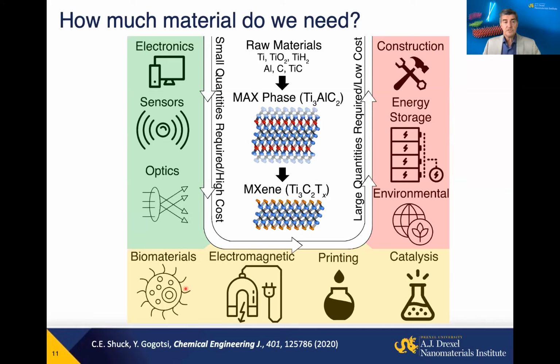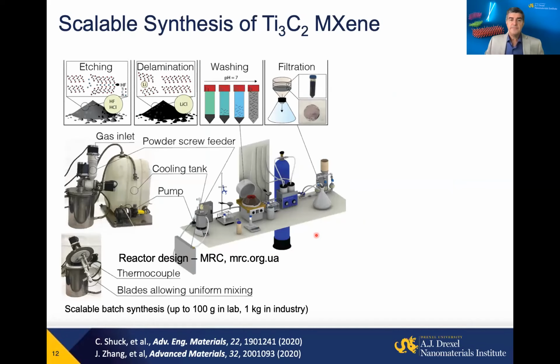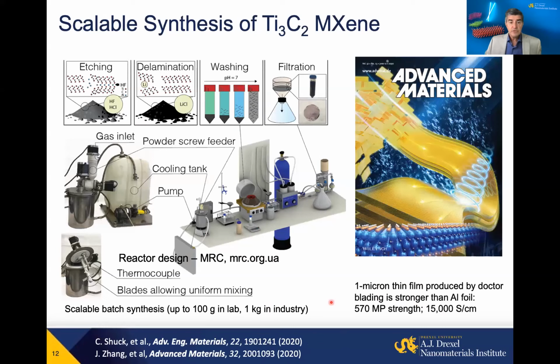But for many other applications, biomedical, antennas, shielding, printed electronics, catalysis, and of course batteries, environmental, construction, we need much larger amounts of materials. And the important thing about MXene synthesis is that from day one, we could make grams of these materials. Now there are 100-gram reactors in our lab, designed for us by a small company in Ukraine and manufactured here. There is a 1 kilogram reactor already available in industry, which scales up. And we can use this material and, for example, doctor blade a slurry of MXene and produce films.